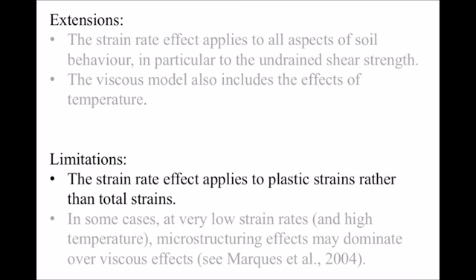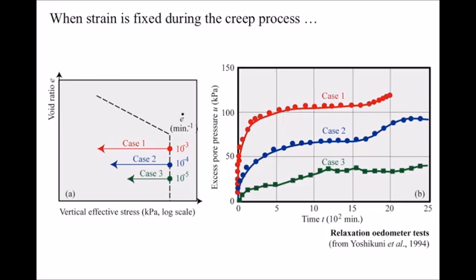Limitations now. The strain rate effect applies to plastic strains rather than total strains. Consequences are relatively small in most cases, but fundamentally it's important to indicate that point. When we have a clay which is during secondary consolidation here, so with a decreasing void ratio, if we stop the strain, in fact the strain is constant, the strain rate is zero, and so the effective stress should be constant. It's not the case.